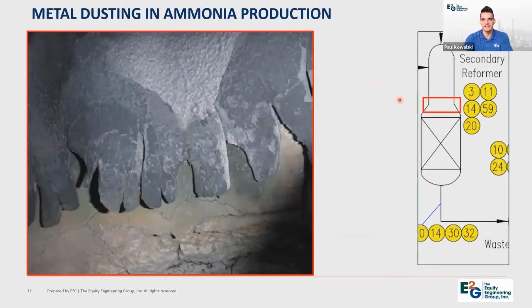And here's another picture in the same location of a secondary reformer, but this is not the same vessel. But again, this is just highlighting the damage. In this case, the burner liner was exposed to the process fluid really on both sides. So really the metal dusting rate is double what it usually would be because it's getting attacked from both sides. And we can see the complete wastage of material here. And again, some damage to the refractory is already being identified, and this can become a large issue pretty quickly for the base material of a secondary reformer. So again, this combustion section in the secondary reformer can be a very severe location for metal dusting to occur.